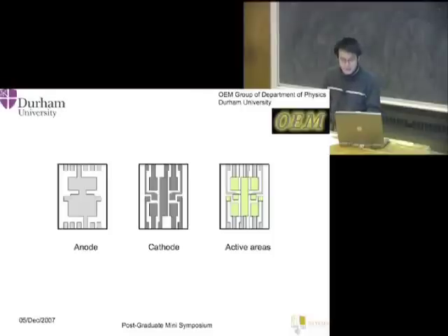And this is the substrate we use for the experiment. This is the pattern of the anode, in this case ITO, and this is the cathode. In my research, I use silver. First is the anode, and then you spin coat the small molecule or the polymer everywhere, and then you cap with the cathode. So this green area is the only active area that will emit light.